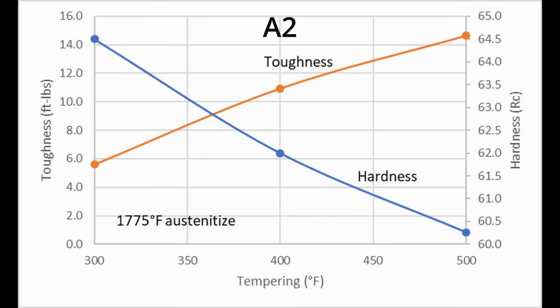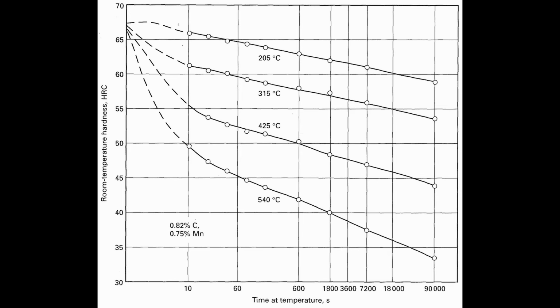But on the subject of time, temperature is more important than time. So here's a chart of 1080 steel. That's a simple carbon steel. And if you compare 205 Celsius, that's around 400 degrees Fahrenheit, with 30 minutes versus 2 hours, it's a difference of like half to 1 Rockwell C. So usually the temperature matters more. So as we go up to 315 Celsius, that drops it like 4 or 5 Rockwell, a much bigger difference than tempering over twice as long.